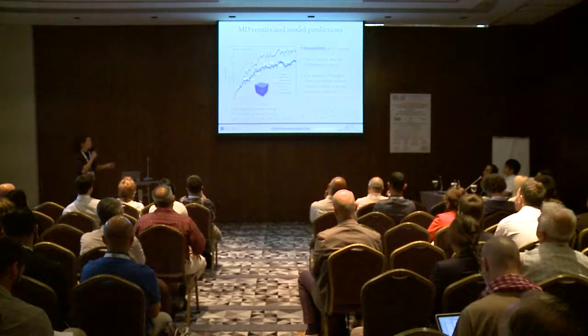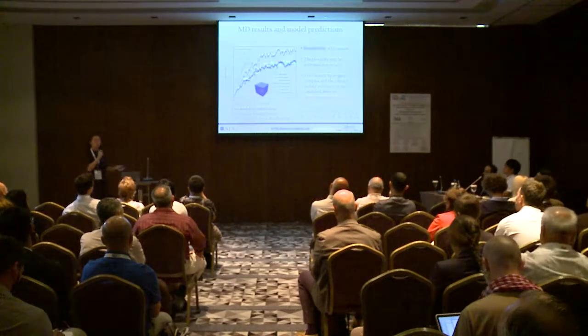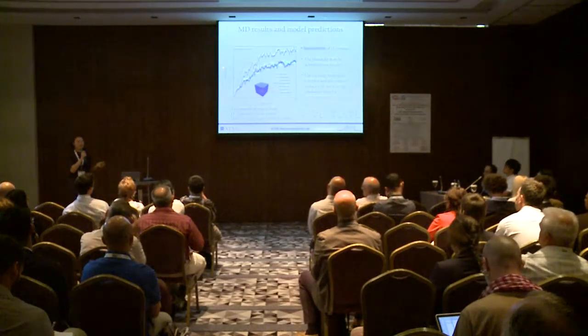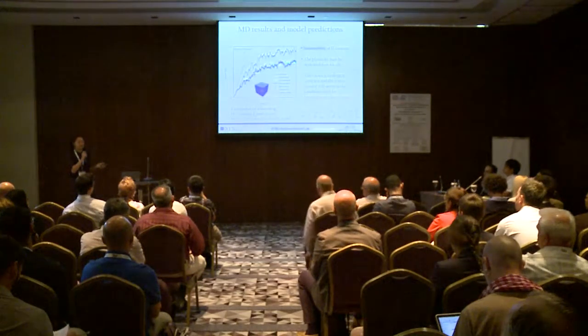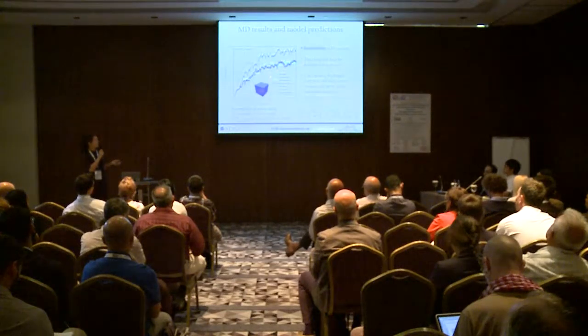That also confirms that the plasticity may activate non-locally, because if homogeneous nucleation applied, it should depend on the hydrogen concentration, but we didn't find this dependence. So it could be non-local plasticity.